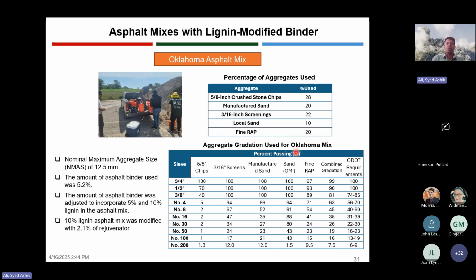Okay. So when we added the asphalt binder to our aggregate, the amount of asphalt binder was adjusted to incorporate 5% and 10% lignin in the asphalt mix. So we had to adjust this 5.2% and make sure the total binder content is 5.2%, where probably 4.9% is the new asphalt binder, and the rest came from the lignin. So we used lignin as a replacement of asphalt binder.